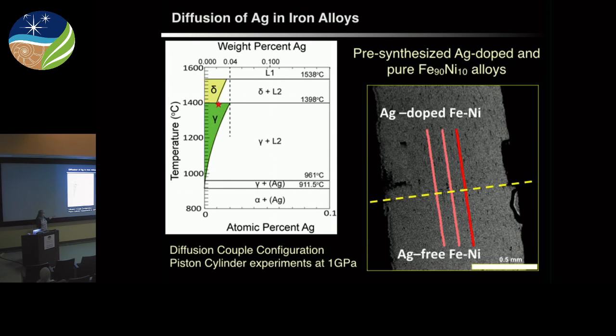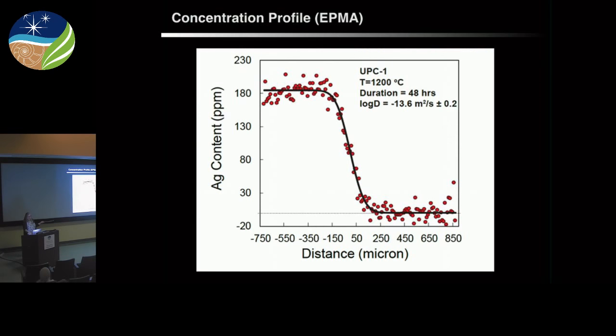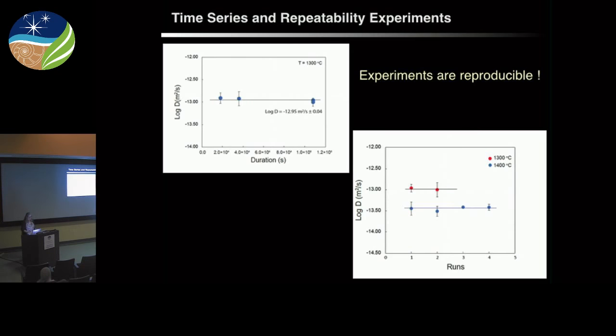So we did pretty traditional diffusion couple experiments, one side doped with a little bit of silver, one side just plain iron-nickel alloys. These were done in the piston cylinder at Union College and also at RPI. They were measured using the electron microprobe. Here's an example of a resulting diffusion profile. It's on the order of a few hundred microns. And this black line or curve is our fit to the data, and it fits the assumption of a diffusion couple geometry pretty well. These were the first experiments I ever did in my piston cylinder at Union, so we did a lot of repeatability experiments, and our experiments are pretty reproducible, which was nice for us.